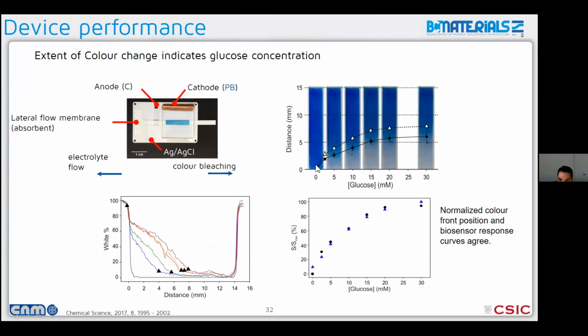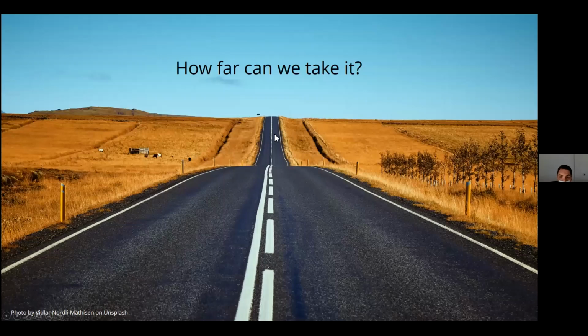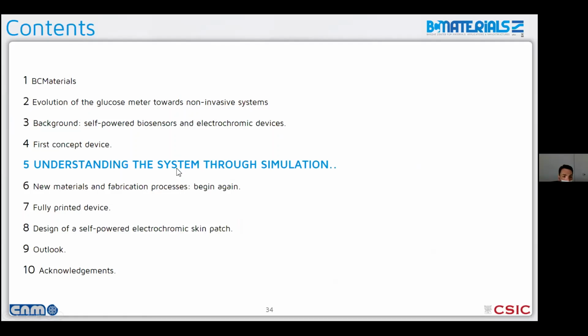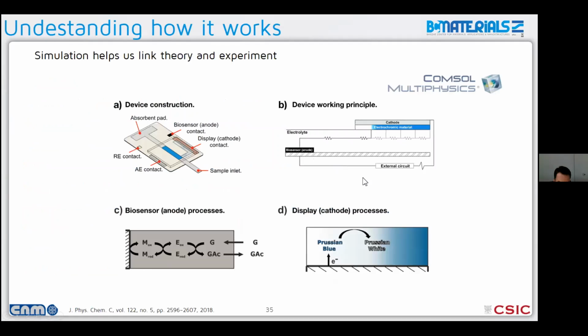And when we compare the curves obtained looking at different glucose concentrations, and we compare them with the response of the biosensor, this is normalized, by the way, you can see that there's quite good agreement. So we were very happy about how this thing was working. So the next thing was to model it, to understand what was going on. So we set up some COMSOL models of the whole system. So we started modeling the biosensor and the cathode individually, and then we combined both models to see how the system would behave.